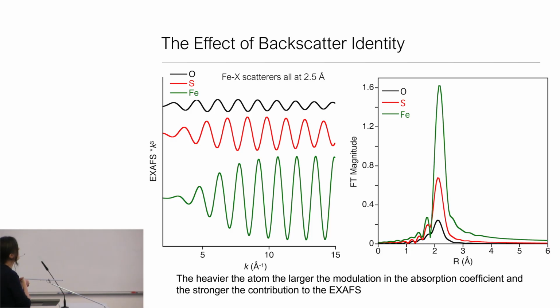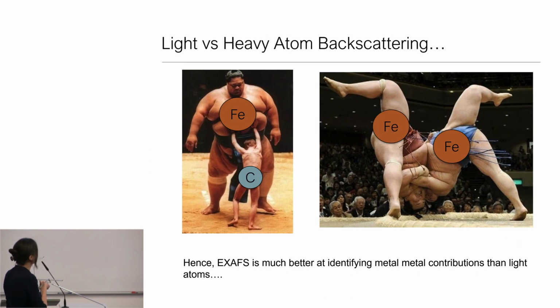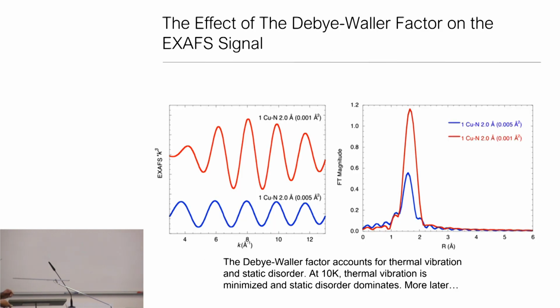When we talk about these amplitude envelopes, what I'm also talking about is the fact that the heavier the atom, the higher in k space it will peak. So there's actually an amplitude modulation that has to do with the effective charge on the atom. The way to think about these modulations even more grossly visually is just that carbon actually can't have a very strong modulation on an iron photoabsorber. That's why these are relatively weak waves, whereas things like metal-metal vectors stand out in XAFS. Those will be very strong modulations, and they're very hard to miss.